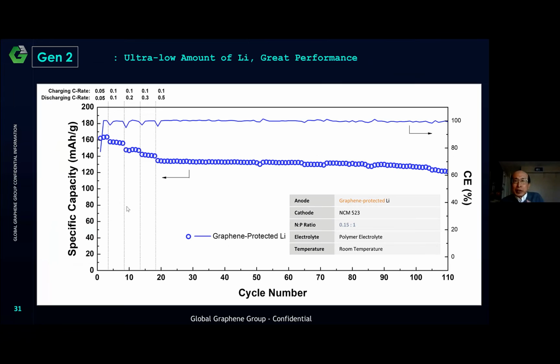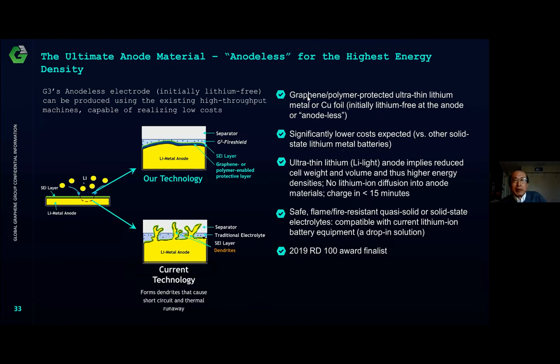In conclusion here, we have been able to develop some so-called anodeless lithium metal batteries, and we have used graphene, sometimes a combination of graphene and polymer, to protect our lithium metal. We can significantly lower the cost of the lithium metal batteries. And because we make use of the very thin lithium anode, or essentially lithium-free in the beginning, no lithium diffusion issue will occur, and therefore the battery can be charged in less than 15 minutes.